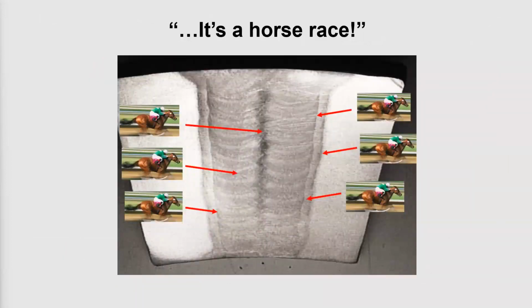So all of that is to say, the message I hope comes out of this is that weldments, when you look at them from a metallurgical standpoint, are incredibly complex structures, with multiple areas where, when the material is being operated at elevated temperatures, they can serve as preferred zones of weakness. And in any given set of circumstances, the zone where the damage may go more rapidly, and so would be the area of primary concern in any type of inspection, can shift from one location to another. And that's what I'm getting at with this. It's a horse race, because in any given situation, any one of these locations could be a preferred location for the damage.